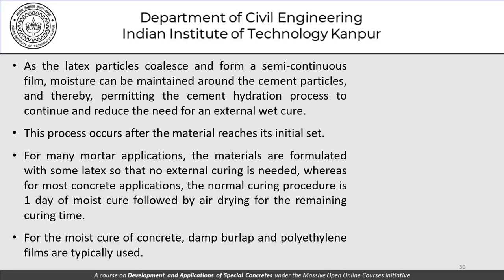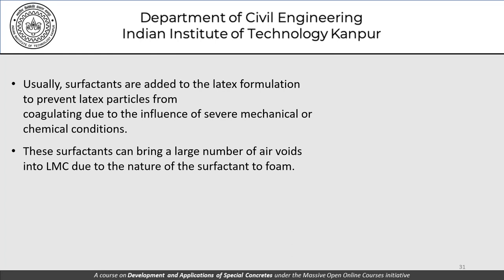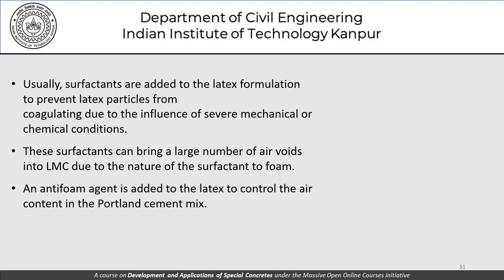Surfactants are added to latex formulations to prevent latex particles from coagulating under severe mechanical or chemical conditions. However, these surfactants can introduce large numbers of air voids into the LMC due to their foaming tendency, so an anti-foam agent needs to be added to the latex to control the air content in the Portland cement mix. This is a practical consideration when using latex particles in LMC.